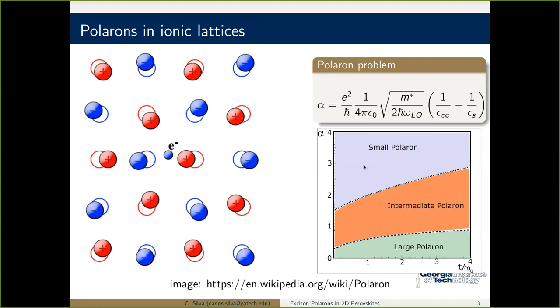There's this parameter that I'm going to introduce here, a mesoscopic parameter that is used to characterize the degree of electron-phonon coupling and the degree of polaronic character. Through parameters like this, you can work out perturbatively, for example, what the polaron binding energies are. The idea is that if you take the difference between the high frequency and static limits of the permittivity, in other words, how dynamic the system is, you have things like effective mass, what the phonon modes involved are, and so on. You can come up with this parameter that allows you to characterize what regime of polaron you are in.